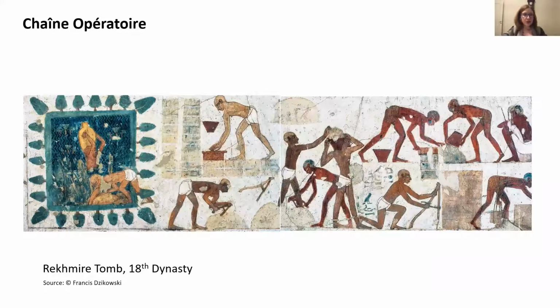To sum it up, back to the comic strip that is giving you the breakdown of the different phases, for the first phase we were able to determine that raw materials can be linked to deposits within a 2-kilometer radius from the core center of the site, which meant that even the manufacturing of the brick could occur nearby the original deposit. Second, when we were thinking about the mixing of the different elements, we could provide evidence that the seagrasses were procured locally from the protopalatial period onwards by just naturally collecting the ones deposited on the shores around Malia.